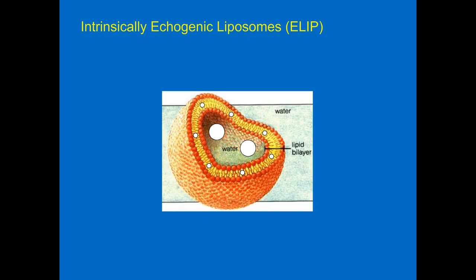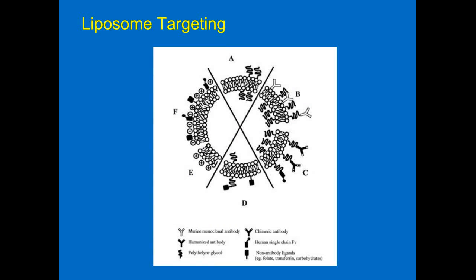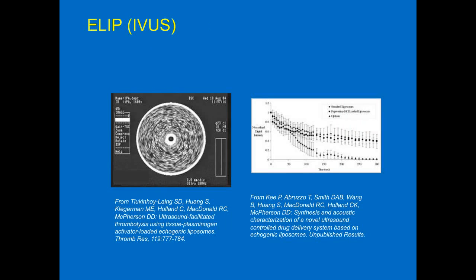And therefore that reflects ultrasound. The gas is usually used because it's highly reflective of ultrasound, and that makes it a contrast agent. The advantage of liposomes is that they can easily be conjugated to ligands like antibodies, usually through the ethanolamine head groups of the phospholipids, so they're very convenient that way.